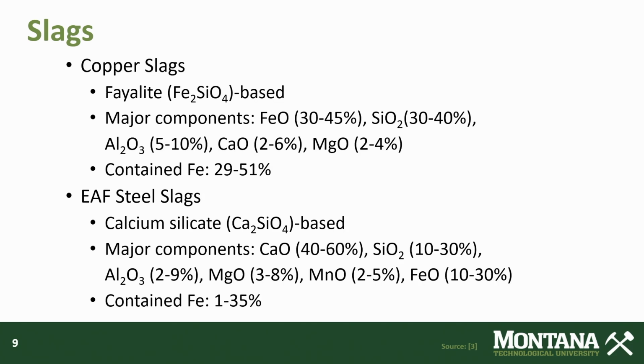So two of the most common waste slags are copper and steel slags. Copper slag is a silicate slag and EAF slag is a calcium silicate slag, and these slags act as repositories for impurities, and some of the impurities contain toxic or hazardous materials, which is why they can be an environmental concern. We can clearly see a wide range of components that make up these slags due to the varying initial feedstocks and processing operations.